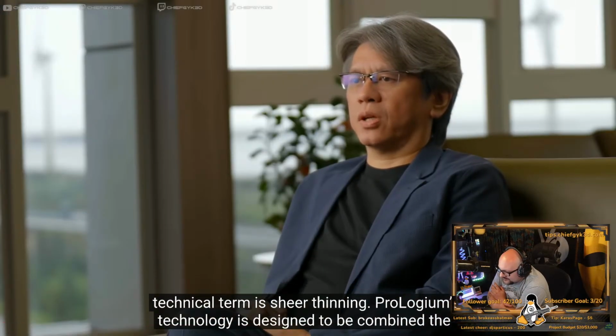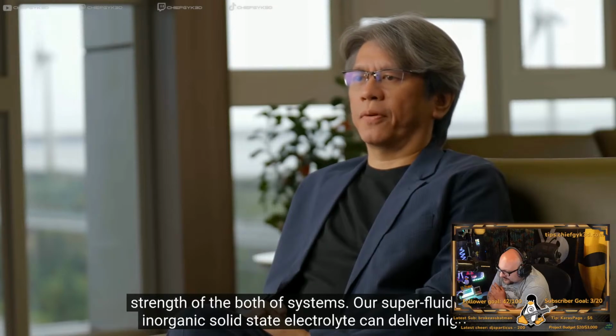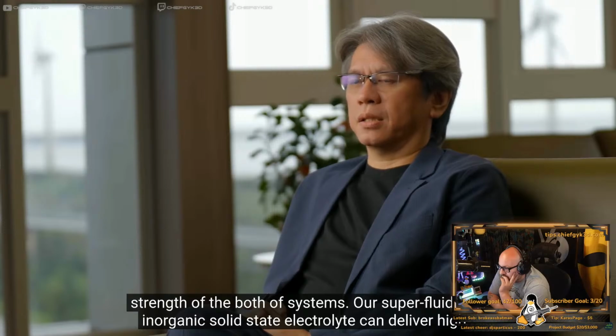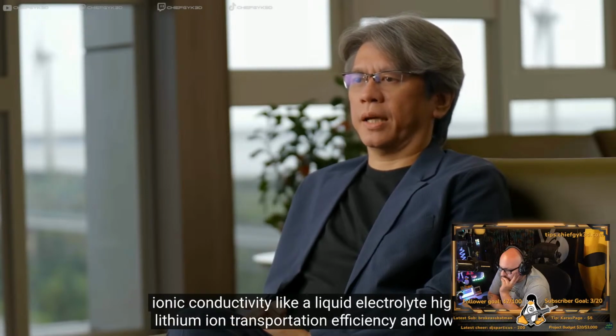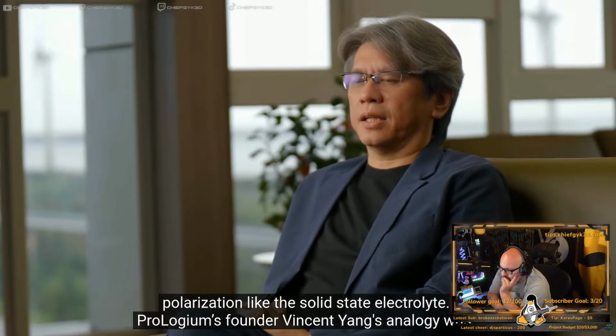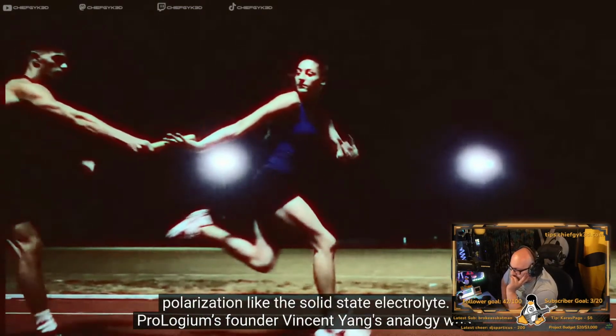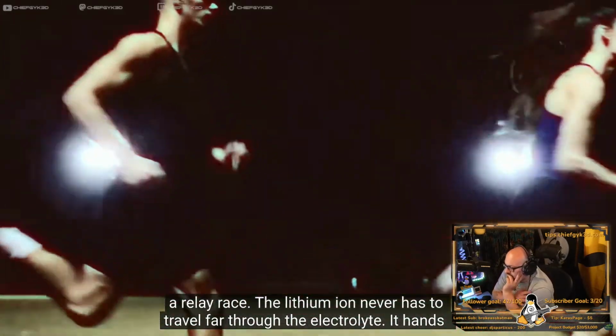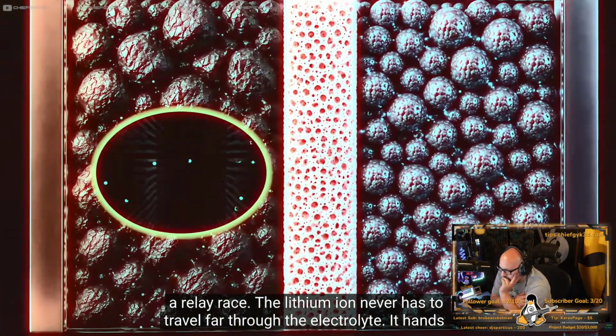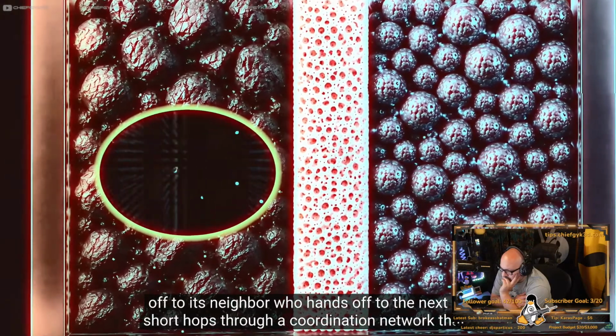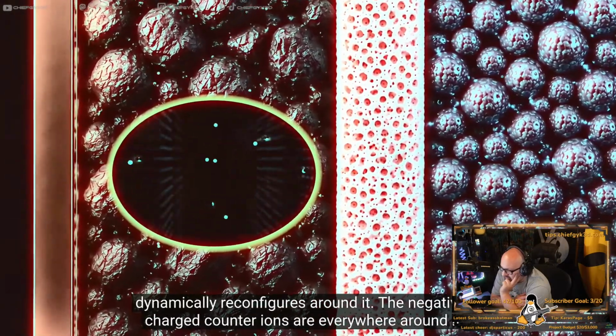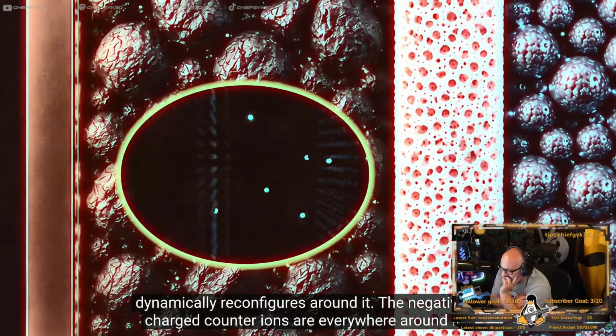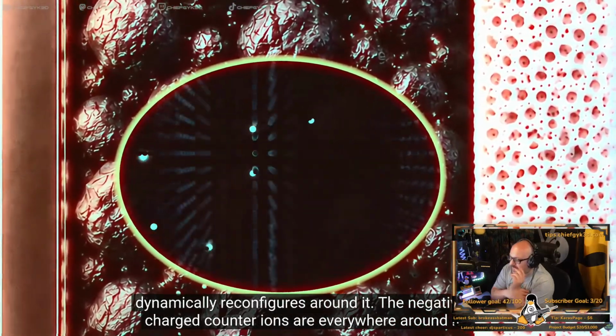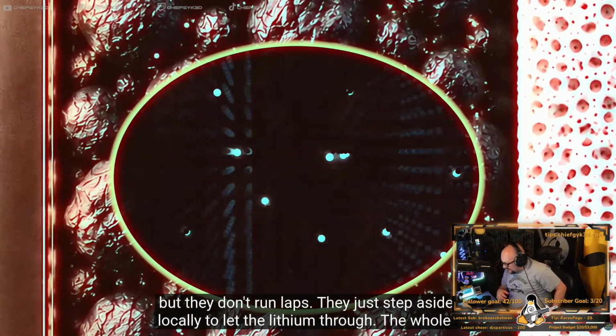Prologium's technology is designed to combine the strengths of both systems. Our superfluidization of inorganic solid-state electrolyte can deliver high ionic conductivity like the liquid electrolyte, and high lithium-ion transportation efficiency and low polarization like the solid-state electrolyte. Prologium's founder, Vincent Yang's analogy was a relay race. The lithium ion never has to travel far through the electrolyte. It hands off to its neighbor, who hands off to the next, in short hops through a coordination structure that dynamically reconfigures around it. The negatively charged ions are everywhere around it, but they don't run laps. They just step aside locally to let the lithium through.